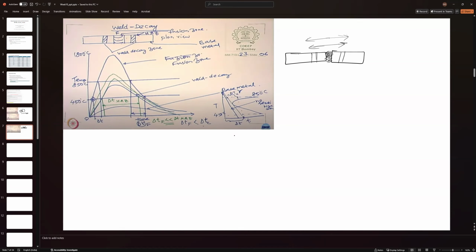Suppose this is a plot. So this is your fusion zone. This welded zone is the fusion zone. In the fusion zone, your metal completely melts, reaching, suppose here, 1800 degrees Celsius. And if you go further away, the highest temperature the metal would have attained would be lower, right? So at some point far away, it won't reach 450 degrees Celsius. It's below that, so nothing happens, nothing in the sense related to weld decay.